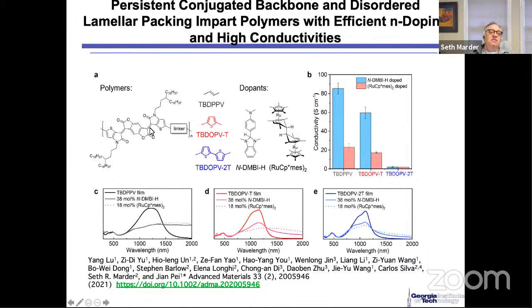This particular case, for reasons that I can discuss, works a little bit better with the hydride than the ruthenium dimer. Well, the bottom line is the ruthenium dimer is too effective and it dopes this thing too quickly in solution, and it doesn't set up the right morphology as it's forming the film. Whereas the hydride is less effective. It doesn't dope until it's in a film and heated a bit. Okay. And as a consequence, we can get this material to form the correct morphology in the film prior to doping.